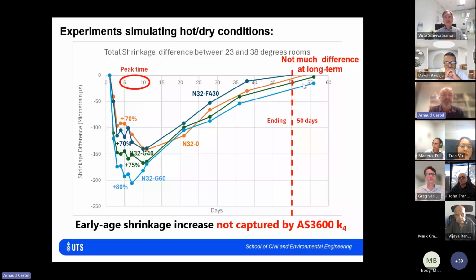So one way is to use the so-called ring test, where you have a concrete ring which is cast around a steel ring. So when the concrete wants to shrink, the shrinkage is restrained by the steel ring. So there are some tensile stresses building up in the concrete ring, and those are sustained, which means there's creep. And creep is in tension, not in compression. And creep is very important because it's actually contributing to reducing a lot the level of stress in the concrete. So it's absolutely crucial to account for tensile creep to calculate the stresses. That's what we're trying to do, and calculate the tensile stresses building up in concrete.